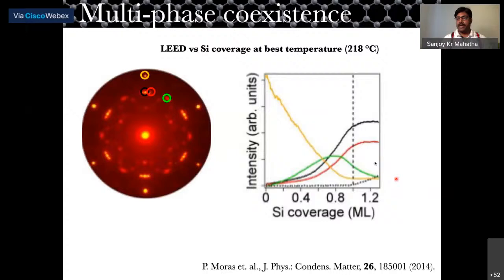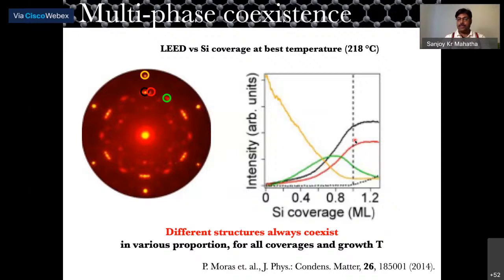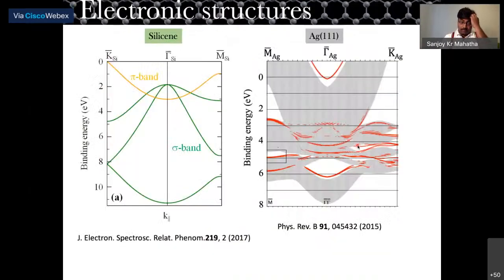Okay, there is a contribution from this root 13 by root 13 also. So that means the single-phase silicene on top of silver 111 doesn't exist. Different structures will always coexist in various proportions, and that depends on the coverage and on the growth temperature. So what one can do is try to minimize the contribution of root 13 by root 13 by playing with the growth temperature, and this is what we did. We grew a film with 4 by 4 and very little contribution from root 13 by root 13.